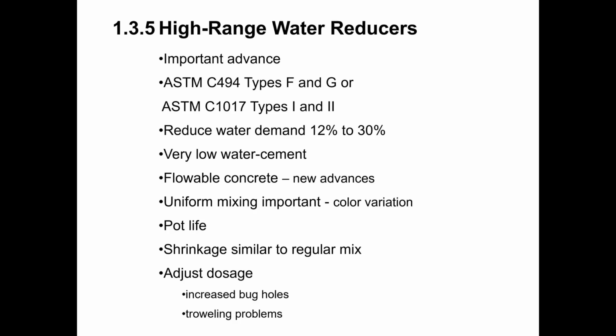So I mentioned the troweling problems due to the texture of the fresh concrete being sticky. Another thing to keep in mind with a high range water reducer is that you may see an increase in bug holes on the surface of the concrete, and that results from just that sticky texture, the concrete sticking to the form and trapping small air bubbles on the surface of the form, which then leads to bug holes. So just some things to keep in mind when using a high range water reducer.